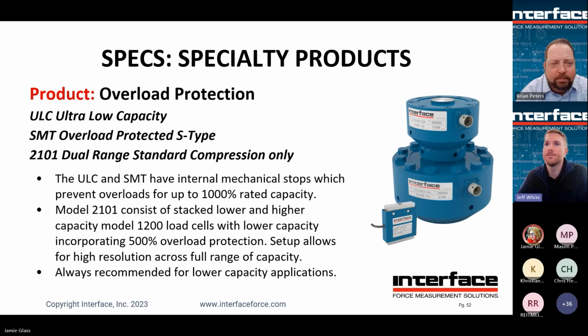So overload protection. Lower capacities often have internal mechanical stops offering very high overload protection. There are a few products to highlight here: the ULC, the SMT, which we mentioned before, and the 2101 dual range standard compression only. The ULC is very high performing, low capacity, and highly overload protected. It also offers side load overload protection of 5 times the capacity, and is very good at ignoring extraneous loads.